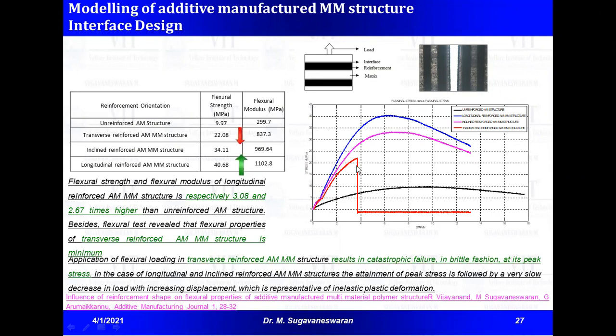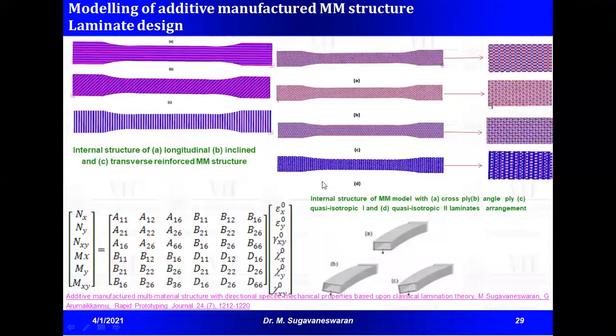But at a later part, I would like to show an interesting result, how we have eliminated or improved this behavior in the unidirectional case. In the multidirectional case, twisting, that is in-plane and out-of-plane curvature, in-plane deformation and out-of-plane deformation, can be controlled by proper alignment of the secondary material within the primary material. So twisting, bending, or a combination of twisting and bending can also be controlled by choosing a proper alignment of the secondary within a primary material.